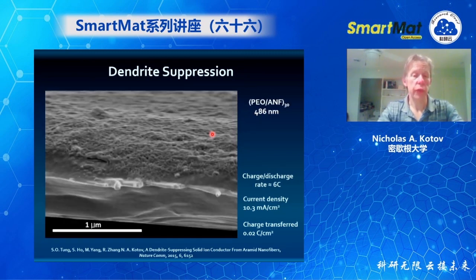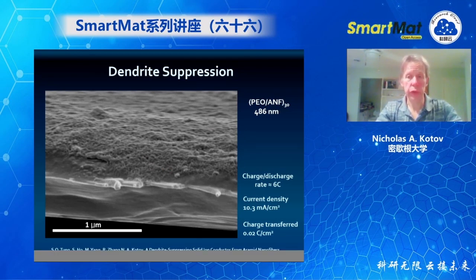And only a few LBL layers is enough in order to suppress completely the growth of the dendrites. And this is done at fairly high C-rate, so it's not gentle growth, it's actually aggressive. And the number of layers is not that big. The thickness is about 500 nanometers. If you compare it with the standard thickness of separators in lithium batteries, it's actually 25 microns.